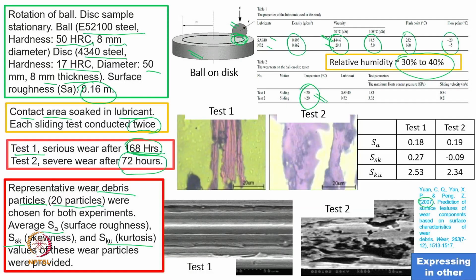That is what they were trying to analyze, and what they found in test 1 and 2 is that the Sa value is more or less the same, while the skewness value in test 1 was on the severe side, on the positive side, 0.27, while in test 2 it is very low, slightly negative, almost negligible negativity. However, the kurtosis values in this case are 2.53 and 2.34. What is the meaning of this?